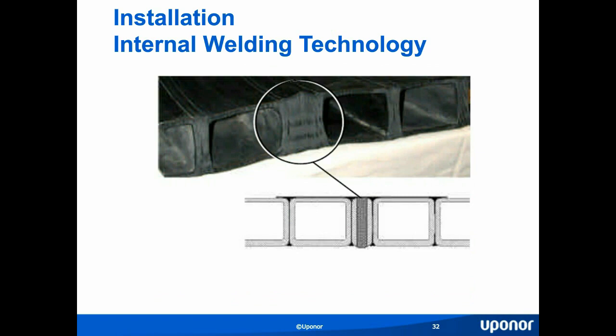Here's a picture of the weld that was produced by the internal welder. You can see the resin goes right clear from the inside through to the outside of the pipe. And that's why we have to use that band to keep the extrusion from pouring out across the outside of the pipe. The weld itself is full profile and therefore much stronger than the pipe itself. You can see the comparison of the weld done by the internal welder versus those little black triangles that are the welds that are produced in the factory.